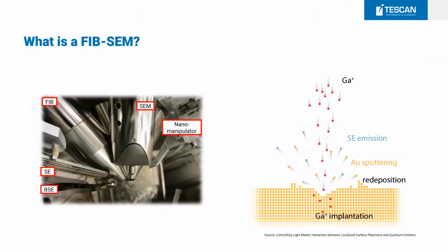So I used two images. The left one is the image from our FIB-SEM. So it's the image inside of the chamber of a FIB-SEM. And you can see that there is a lot of stuff inside of the chamber of a regular FIB-SEM. So we have a SEM column, which gives us the imaging. We have a focused ion beam column on the left-hand side, which does the milling. We have two detectors, SE and BSE, which we use for detection and therefore for the imaging. And we have a nanomanipulator. So we can do a lot of interesting and exciting stuff with our FIB-SEM.